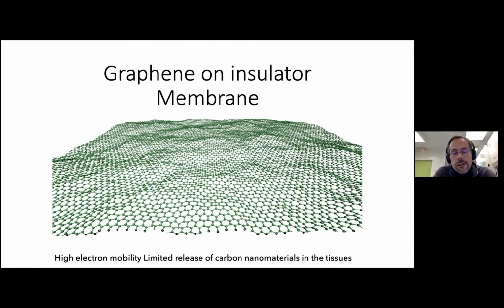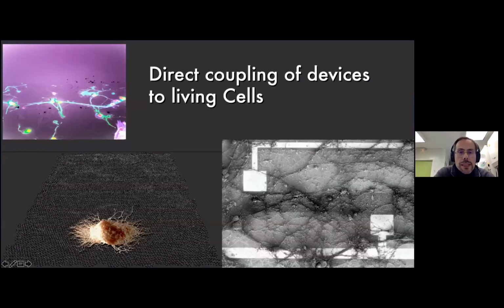So in the rest of my talk, I mostly speak about this type of graphene, which is a mosaic of polycrystalline graphene, even though here it appears like a single crystal, but it's a monolayer on top of a polymer, which is biocompatible. In the beginning, we decided to use monolayer graphene as a substrate, and we started by making growth of neurons on graphene to try to record the neuronal activities. So that was a very fundamental project in the beginning.